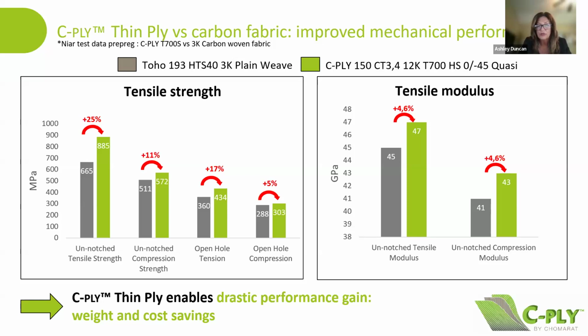The results showed that C-ply outperformed the traditional 3K woven fabric in both tensile strength and tensile modulus, while also delivering weight reduction, 200 GSM versus 150 GSM areal weights. So in other words, the C-ply thin ply laminate provides the best of both worlds: improved structural performance combined with lower weight.